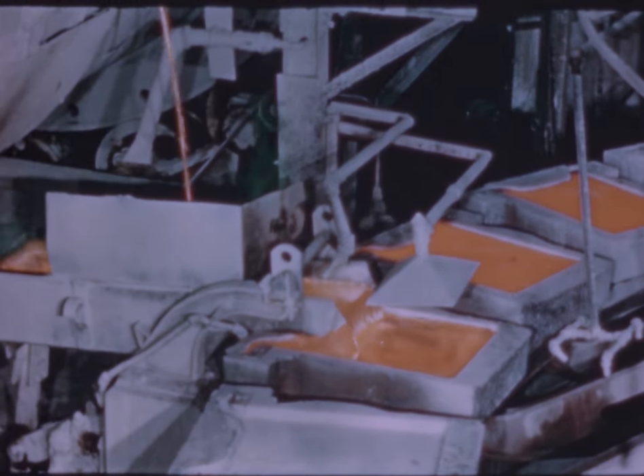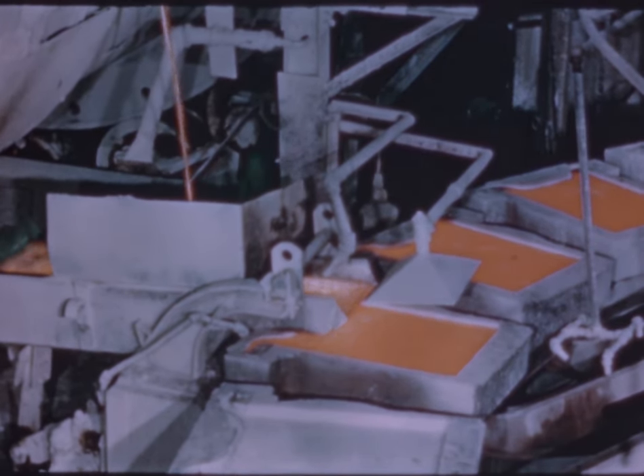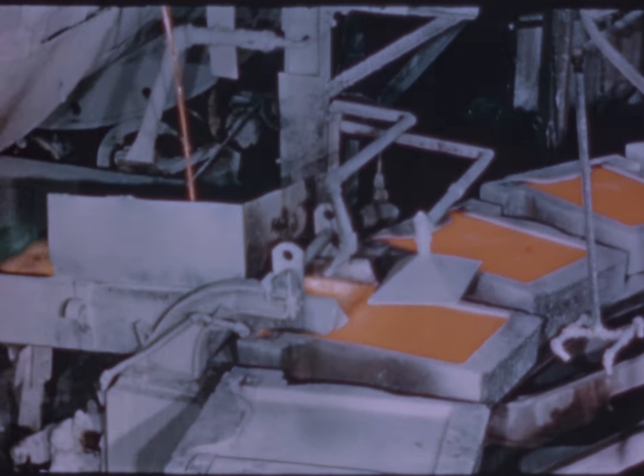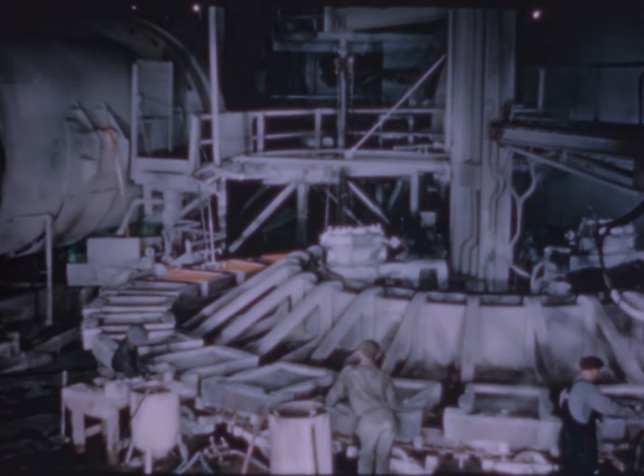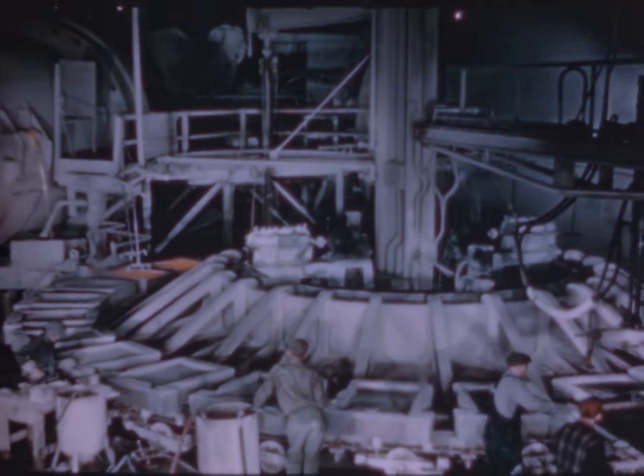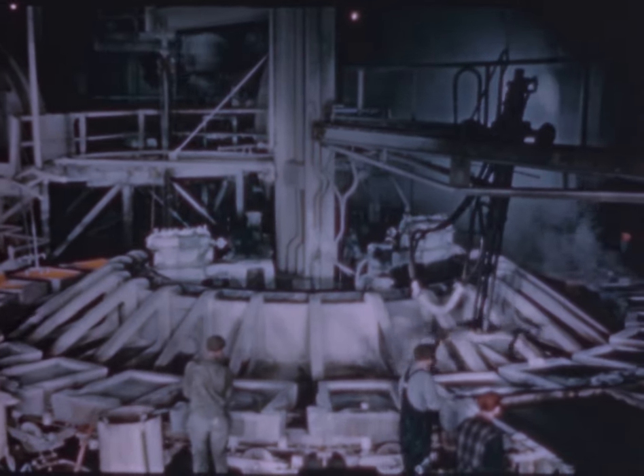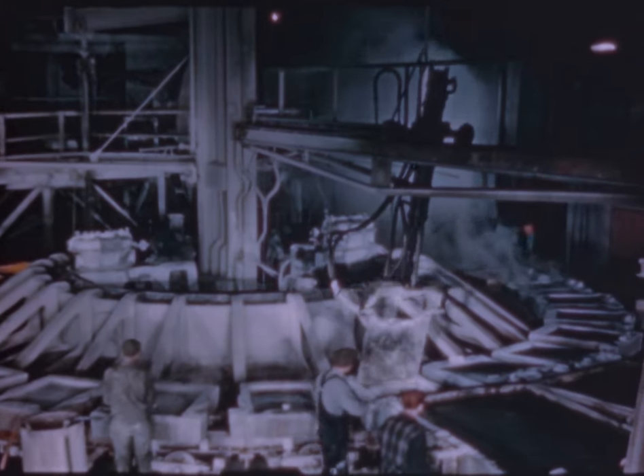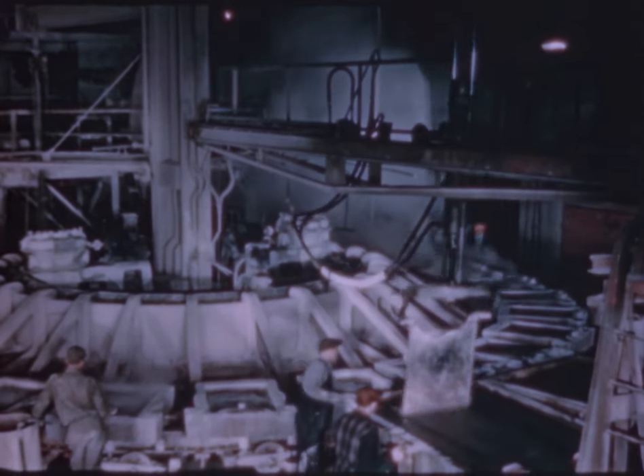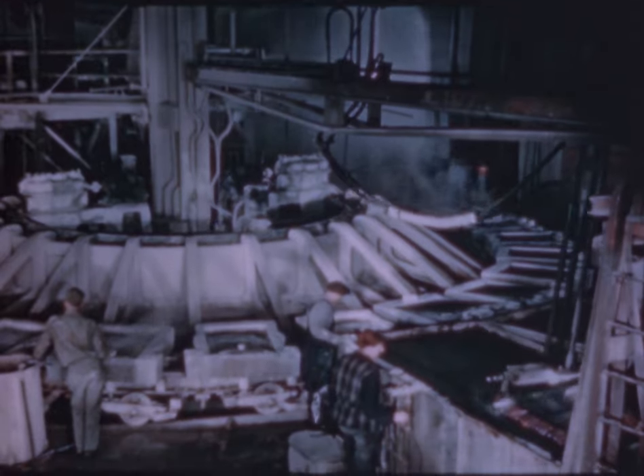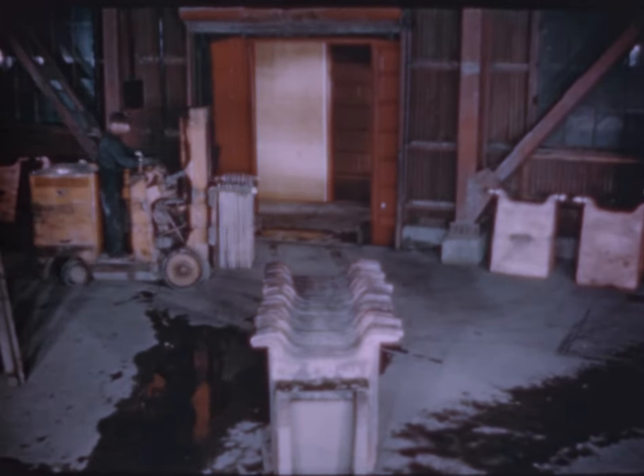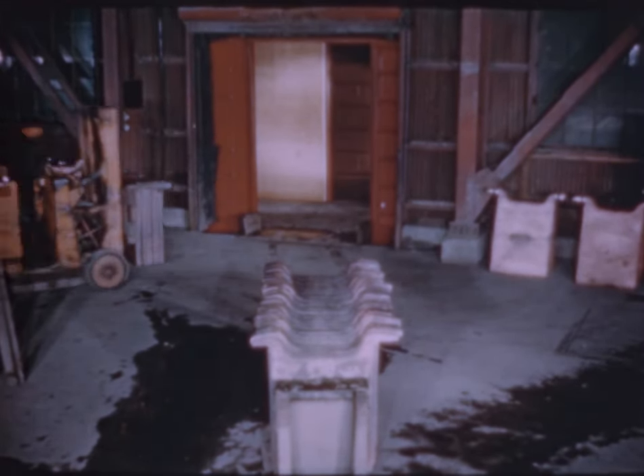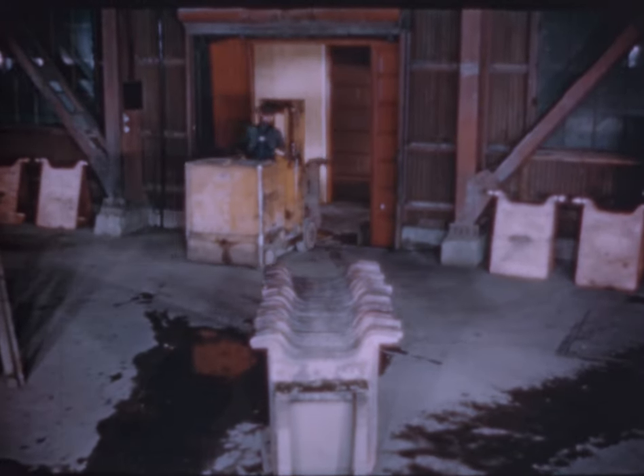Because copper solidifies so rapidly, it is run into a pouring spoon, which holds just enough to fill one mold. By the time the casting wheel has made half a turn, the cast anodes can be lifted and quenched, and the molds prepared to repeat the cycle. While the anodes are being packed in boxcars for shipment to the electrolytic refinery at Great Falls, we'll take a look at some of the other operations performed here at Anaconda.